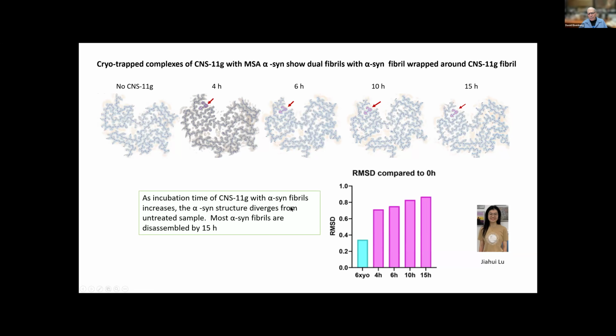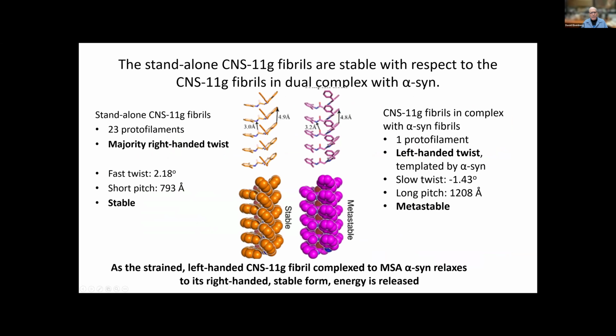And when each of these structures is compared to the structure without any small molecule, you can see that they diverge increasingly from the untreated fiber, as though the fiber's already starting to unfold under the treatment of CNS11G. So through other work, we've learned that the standalone fibers that I showed you that were first seen, those fibers are more stable than the ones that are complexed with the alpha-synuclein protein. So the alpha-synuclein protein fibers are metastable, and they want to relieve that strain by collapsing into the stable structure. So that's what we think is important in taking apart the fibers.